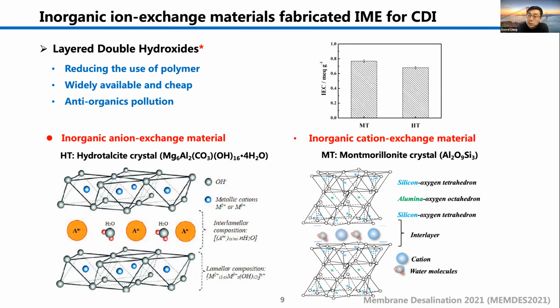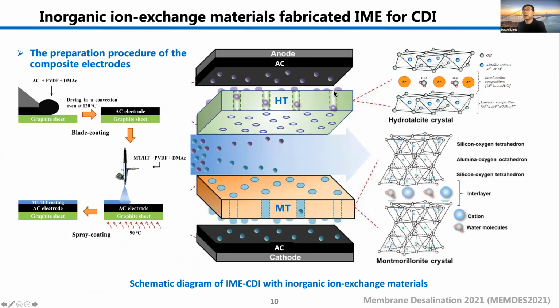What's more, they're quite widespread, cheap, and easy to obtain. They also have very good ion exchange capacity, very high IEC. So this is the whole diagram of the IME CDI with inorganic ion exchange materials. The fabrication is just to first make the AC layer, the AC electrode, and on top of it, spray coat ion exchange materials. And finally, we obtain the selectivity for specific ions.